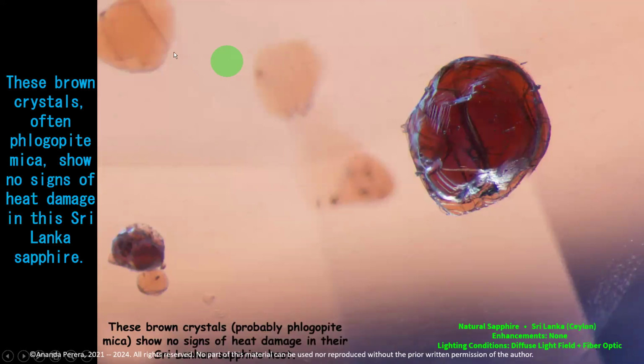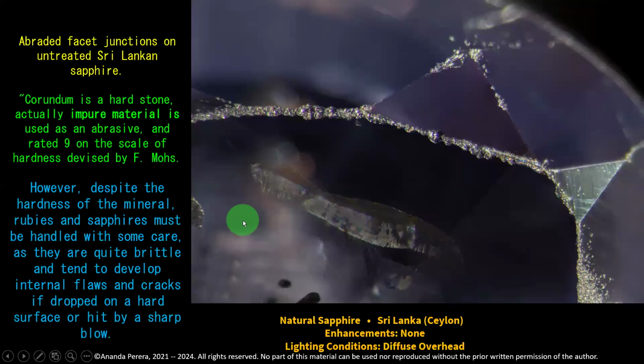This brown crystals, there are so many crystals you can see here. The lighting condition here is diffuse light field plus fiber optic. There are two lighting conditions together. Look at the differences here. You can see the brown crystals. All are Phlogopite mica. No signs of heat damage. No signs of heat damage for this fingerprint and every crystal here. So it shows us it is natural sapphire. We'll go to next.